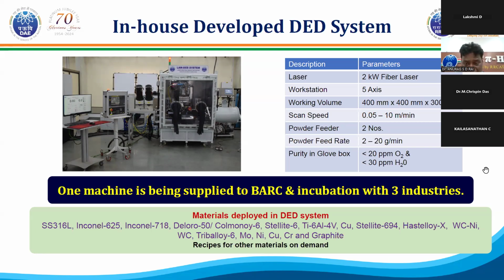The feed rate is in the range of 2 to 20 gram per minute, and everything is in a glove box, where purity level by continuous purging can be achieved at less than 20 ppm of oxygen and less than 30 ppm of moisture. So this can be done. We have developed many materials of our requirement. For example, SS316L, 625, 718, Deloro 50, Colmonoy 6, Hastelloy, Titanium 64. Many materials we have tried, and the team has expertise now. They can develop many applications for this.